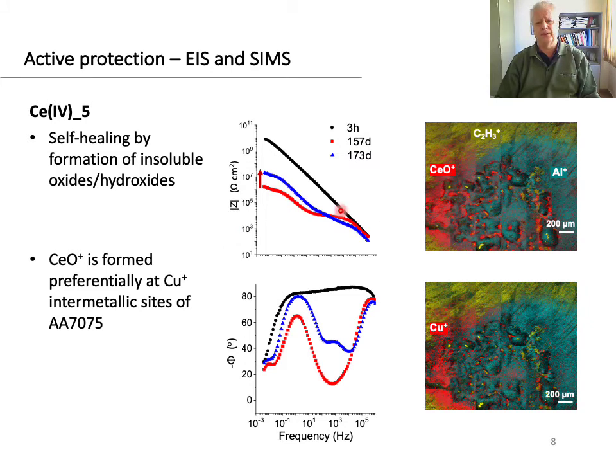More insight on the regeneration process was obtained by ToF-SIMS surface analysis. The overlay maps of aluminum, cerium oxide, and PMMA ionic fragments reveal the formation of cerium oxide within the pits. These are the red zones here, at these points marked in red, in the pits that block the progress of the corrosion. Interestingly, there is a spatial correlation between copper of the intermetallics of the aluminum 7075 constituent and cerium oxide fragments, indicating that the formation of cerium oxide is favored by copper intermetallic phases that contribute to the cathodic protection in the defective zone.